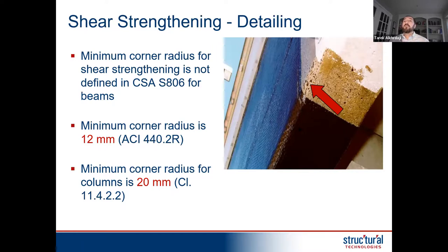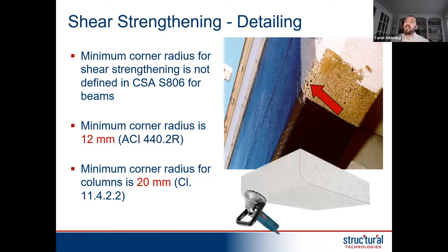And the other thing is for columns. Sometimes you increase the shear strength of columns, so you wrap the column to increase shear capacity. The corners for columns need to be rounded to close to 20 millimeter in radius. Again, the idea is I'm trying to prevent stress concentration that can lead at some point to premature failure at higher stress level. So these are detailing, not really a design requirement, but a detailing requirement to ensure the design intent is achieved.